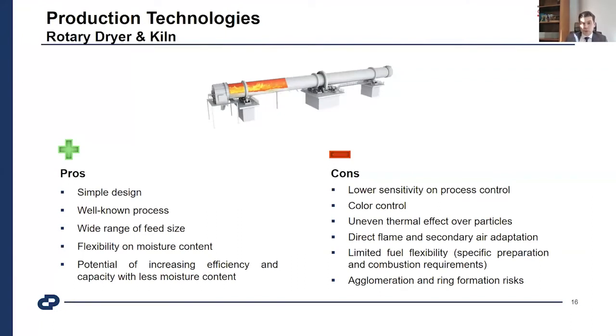Secondary air: direct flame, and fuel flexibility is a little bit limited, because in direct gases the flame is controlling the process. It can be adaptable, but compared with the other solution, it's a little bit complicated. Also, if the heat process cannot be controlled well, there are agglomeration and ring formation risks, and they may also cause process faults and failures of the system.